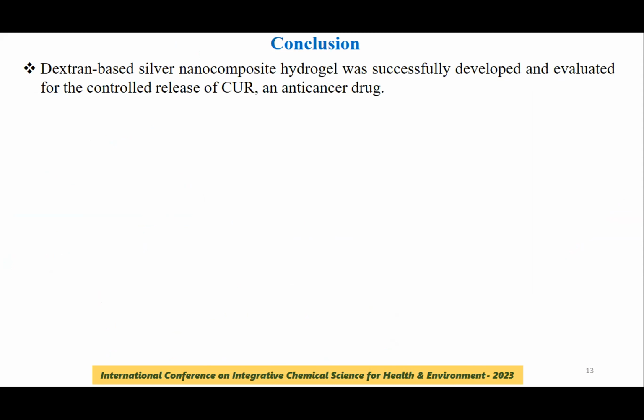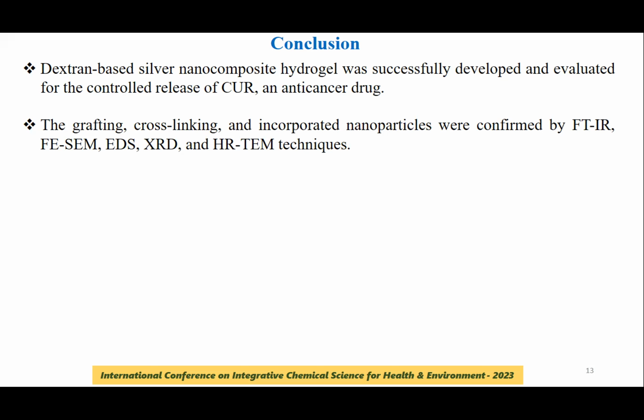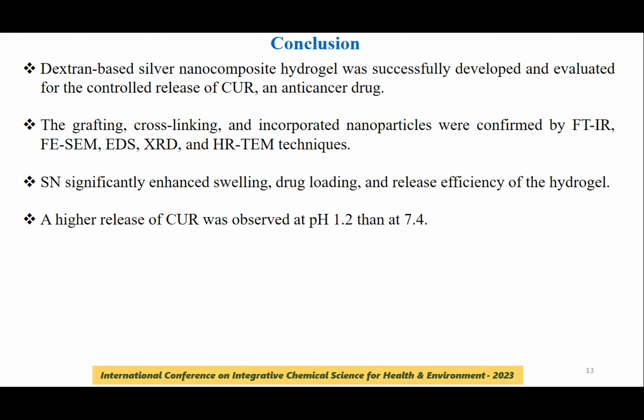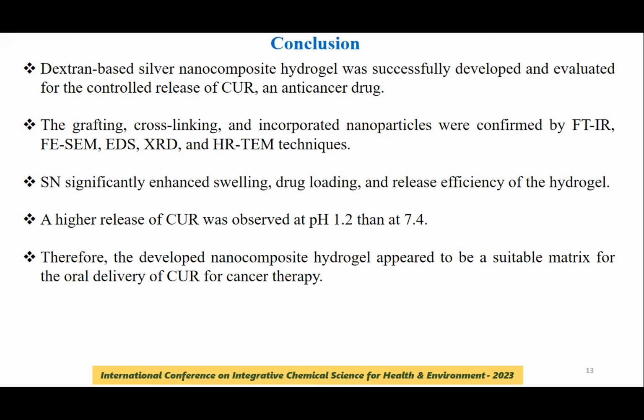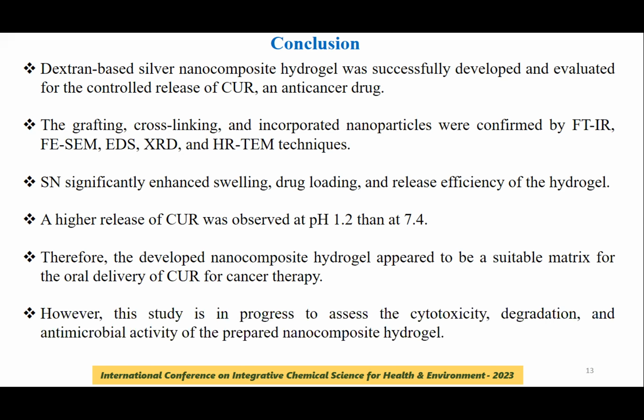To conclude, dextran-based silver nanocomposite hydrogel was successfully developed and evaluated for controlled release of CUR, an anti-cancer drug. The grafting, cross-linking, and incorporated nanoparticles were confirmed by FTIR, FESEM, EDS, XRD, and HRTEM techniques. Silver nanoparticles significantly enhanced the swelling, drug loading, and release efficiency of the hydrogel. A higher release of CUR was observed at pH 1.2 than at 7.4. Therefore, the developed nanocomposite hydrogel appeared to be a suitable matrix for oral delivery of CUR for cancer therapy. However, this study is in progress to assess cytotoxicity, degradation, and antimicrobial activity of the prepared nanocomposite hydrogel. Thank you very much for your attention.